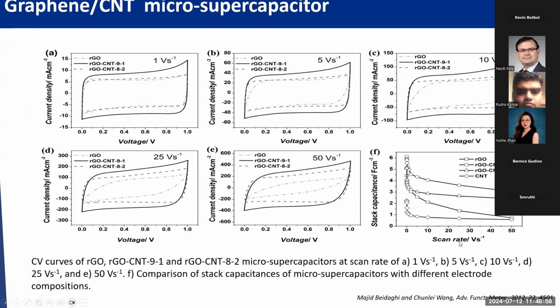And from figure 5, you can see pure CNT, the bottom curve, the diamond-shaped curve. You can see it has a minimal capacitance. So this capacitance actually is the stack capacitance, not the footprint area. We use volume for this case. And you can see the pure RGO is much higher than pure CNT at different scan rates. But at a higher scan rate, 50 volt per second, RGO and CNT both have pretty bad performance.